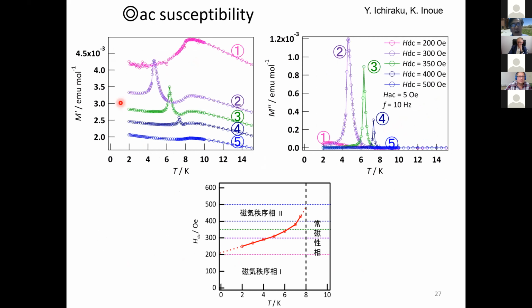If we measure the AC magnetic susceptibility on this anomaly, yes, here is a low field. You can find here is TN. They are going to antiferromagnet. And if we increase the magnetic field, you can find here is TN, but you can find additional anomalies here. If we increase the magnetic field, this temperature is increasing, and finally it disappears. If we plot chi double prime, you can find it very clearly.